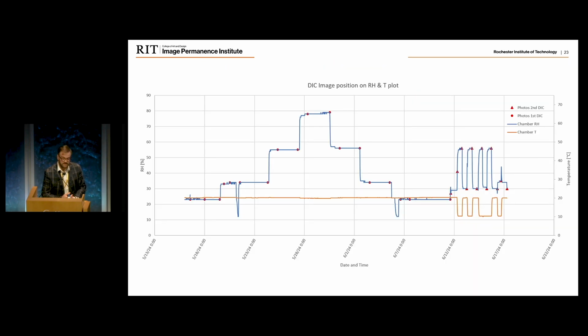So what we've done is basically subjected those samples to pretty much the same RH fluctuations in our walk-in chamber that has strict environmental controls. We just allowed them to acclimatize and relax more than in the DMA. This is 3 days, so we allowed them 3 days of relaxation at each RH level. The red dots you're seeing are the images that I've taken for analysis. The images were actually taken every 15 minutes, but you don't need that many. You just need those at the critical points. So this was the first part, and then the second part, you can see 12-hour fluctuations with and without constant dew point.